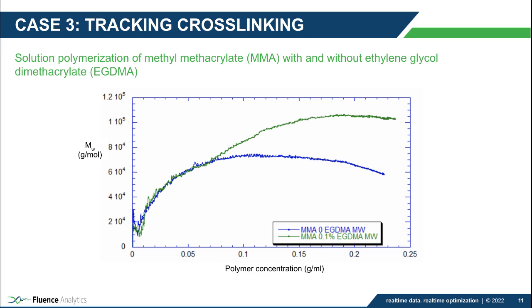Here, we can see the comparison of molecular weight calculated by ACOMP during monitoring of solution polymerization of methyl methacrylate with and without the cross-linker. ACOMP may also help when assessing optimal cross-linker amount for desired molecular weight, as well as optimal cross-linker addition time, allowing for easy visual inspection of the results in real time and fewer reactions.